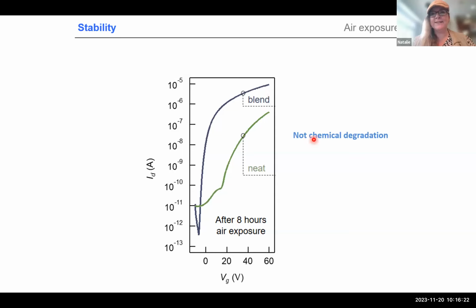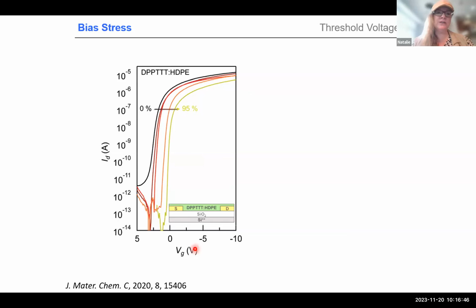What we thought is this is not chemical degradation, because we could not see why adding polyethylene should prevent chemical degradation. So we assumed it has to do with traps. So if you expose the neat material to air, you create traps, and therefore you essentially make your device slower. So we looked into detail.